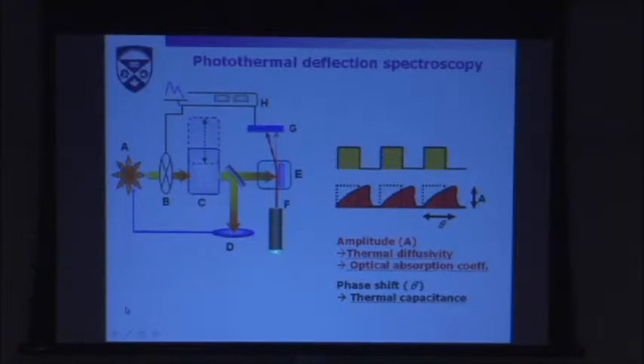And so with the grazing laser, grazing the surface of the sample, basically you have a lensing effect, a deflection, when you have the thermal gradient. So if I am pulsing light, the light from this laser gets deflected, like this, after the pulse. And this can be measured by a position detector connected to the chopper or to the pulsed laser by a lock-in amplifier. That's the drill of doing photothermal deflection spectroscopy.